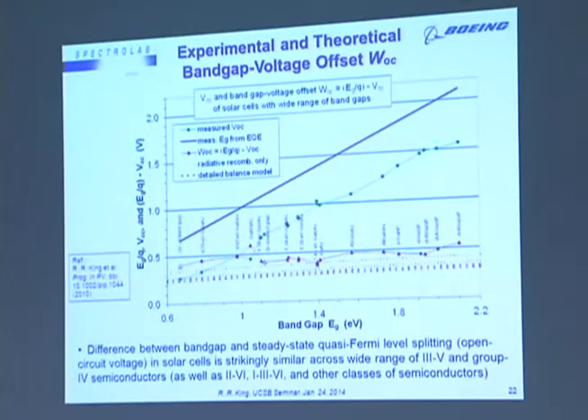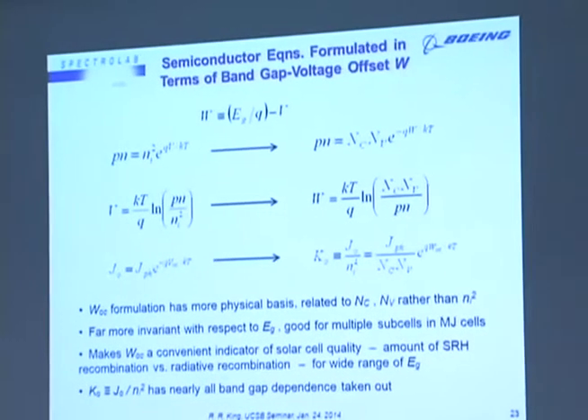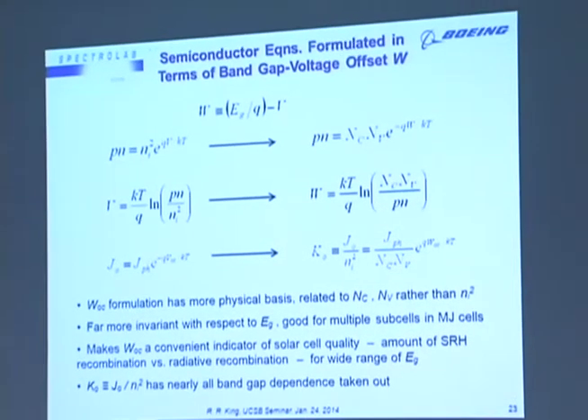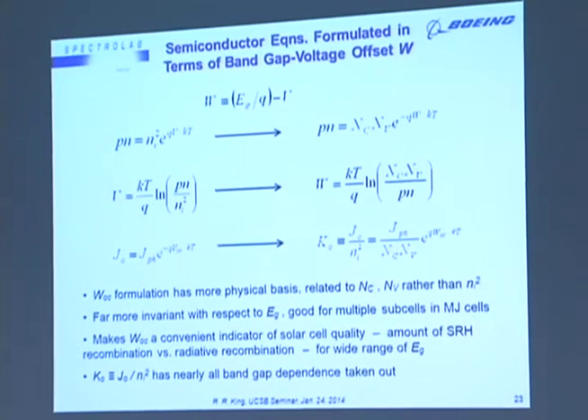So the open circuit voltage is shown in green, the band gap is in blue, and as a function of band gap, this band gap voltage offset is very near the 0.4 to 0.5 range for a wide range of semiconductors. And that has to do with the similarity of density of states in the conduction and the valence band. So when you're working with multi-junction cells and you have a large number of band gaps that you're dealing with, the diode saturation current density, J0, can vary widely depending on that band gap. So it becomes harder to gauge whether you have a good J0 or not so good J0, because that changes so much with band gap.